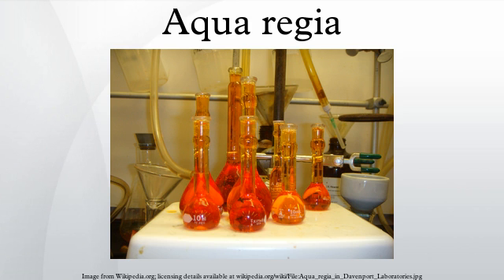Dissolving platinum solids in aqua regia was the mode of discovery for the most dense metals, iridium and osmium, both of which are found in platinum ore and will not be dissolved by the acid, instead collecting on the base of the vessel. When platinum group metals are purified through dissolution in aqua regia, gold is precipitated by treatment with iron chloride. Platinum in the filtrate as hexachloroplatinate is converted to ammonium hexachloroplatinate by addition of ammonium chloride — an extremely insoluble salt that can be filtered off; ignition converts it to platinum metal.